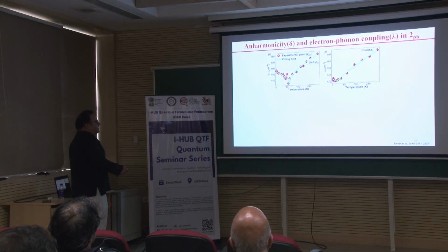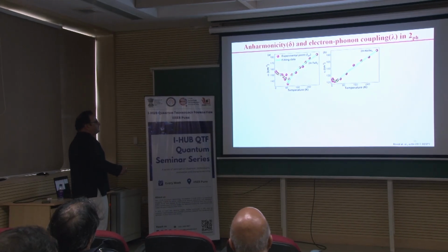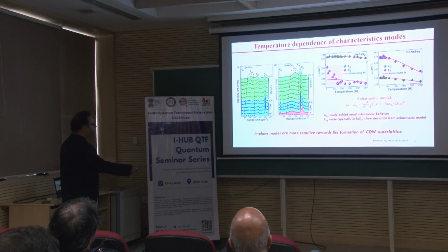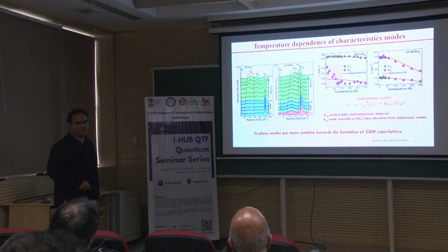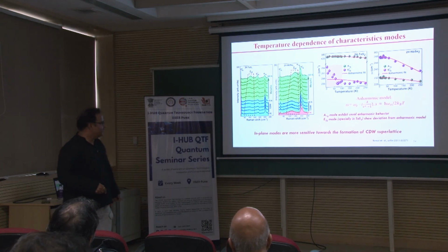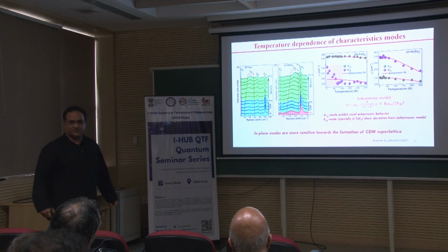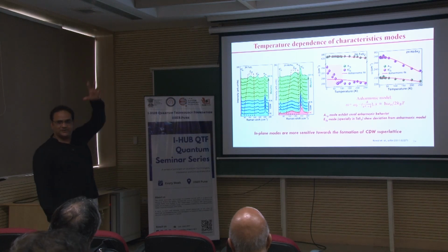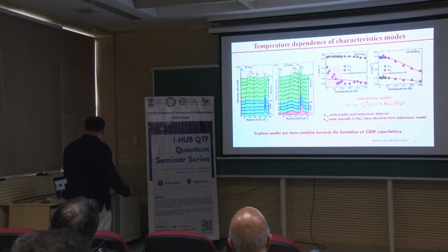Most important here is that if you look at the deviation, the EG modes involve too much deviation from the anharmonic model. So, these in plane modes are more sensitive towards the charge density wave superlattice formation, because the charge density wave is perpendicular to that. It is a one dimensional charge density wave there.